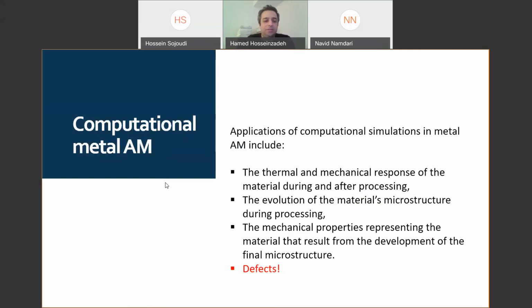Another important subject is the defect. The current simulation techniques and computational methods that I explained in the previous slide cannot simulate defects accurately. Some kinds of defects in the melt pool could be predicted by simulation if we use fluid dynamic simulation, but they're very, very limited to one or two layers. We cannot extend it to the whole sample, because if we want to use fluid dynamics with the resolution of the metal powder and capture one track of a layer, for example in the SLM method, and use a surface method to capture the formation of the surface of the liquid,